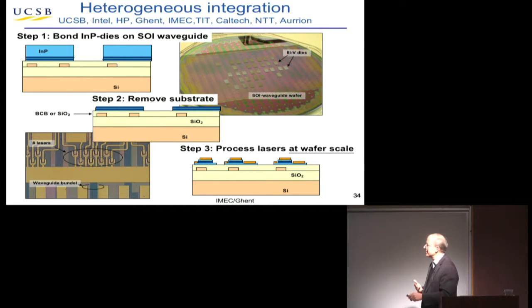Most companies put down pieces of III-V, and there's two reasons to do this. One is that the cost of the III-V is a significant part of the total cost. As you'll see in some later examples where you can see the individual photonic structures, the regions where you need gain, lasing, is pretty small. Most of it's taken up by things like WDM combiners and demultiplexers. So this is an example of where you're putting these materials down on sort of 25% of the area. That cuts the cost down by a factor of 4.